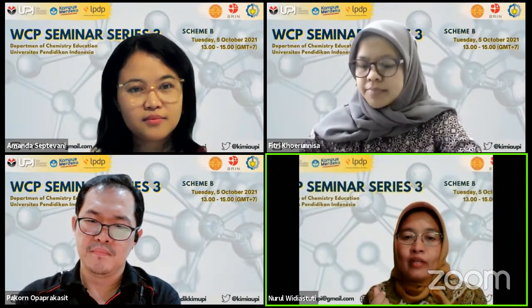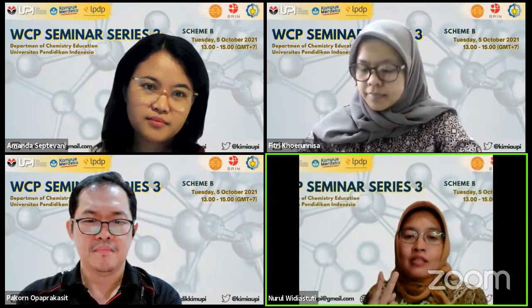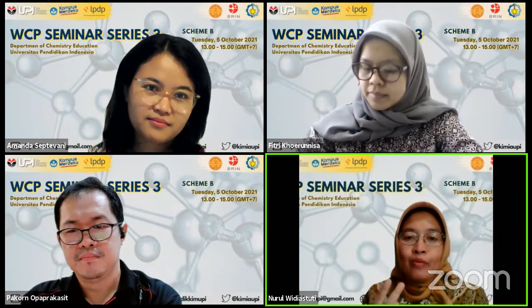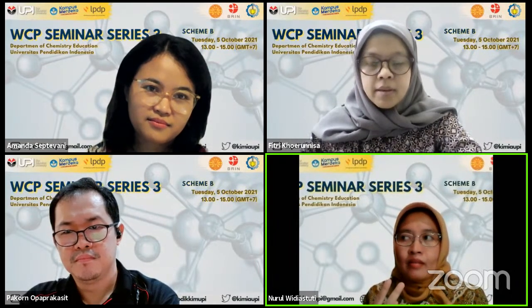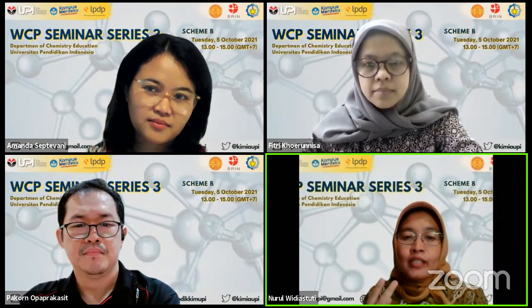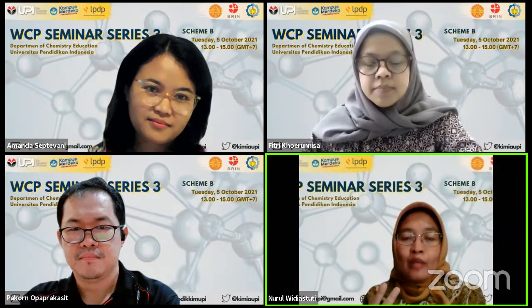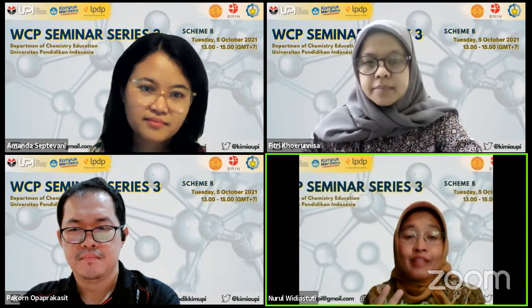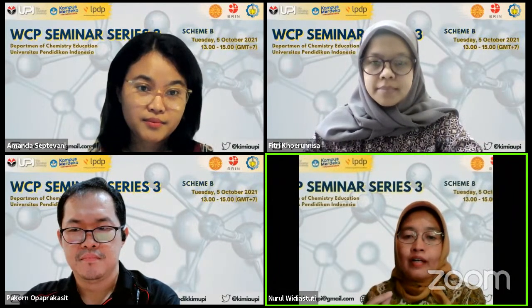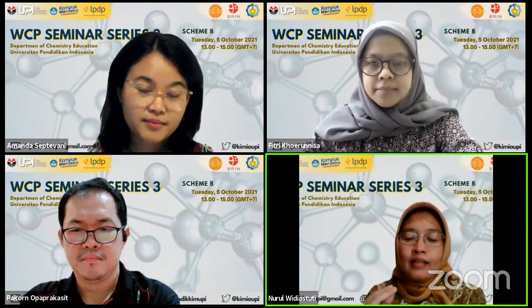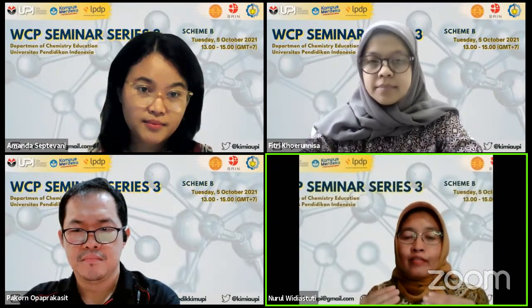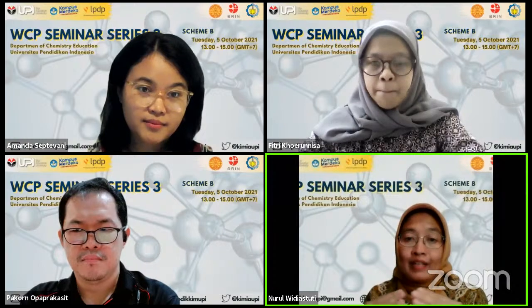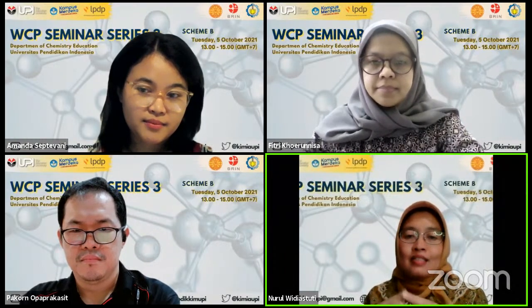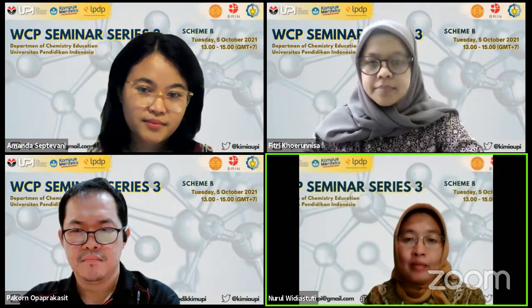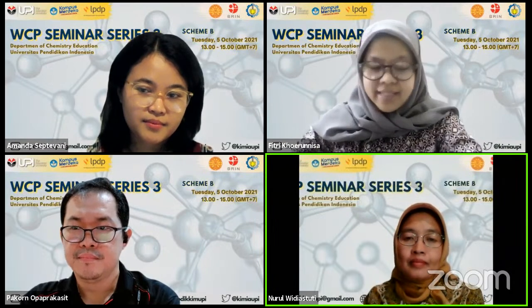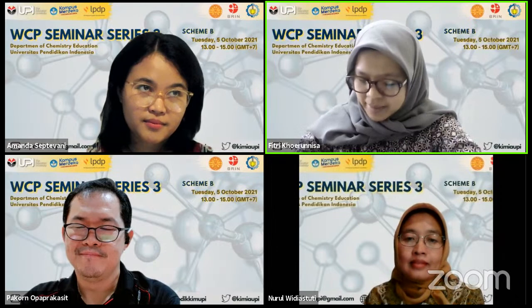So the zeolite templated carbon has two properties combined, from the zeolite and from carbon itself. With the carbon, we know that the surface area of zeolite templated carbon is much higher compared to activated carbon, or even the zeolite itself when used as a filler. And the properties of the carbon can reduce the voids that can appear due to the interface of the filler and the matrix of the membrane. So that is the benefit of using zeolite templated carbon in this case.